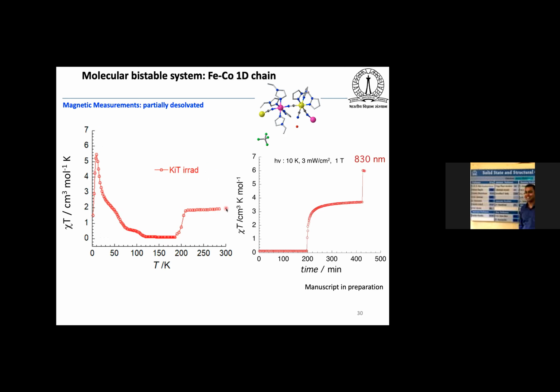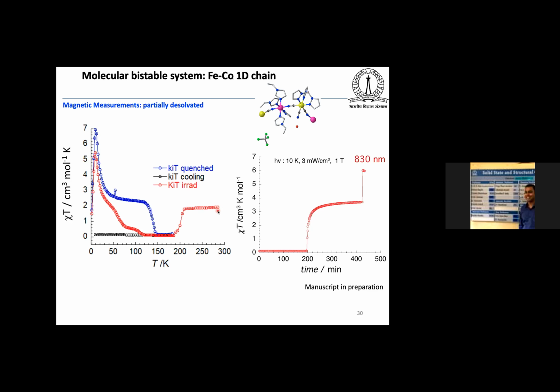And then when you increase it again to high temperature, because using this photomagnetic setup we cannot go to very high temperature, we have not measured it above room temperature. But we have performed this measurement using normal DC measurements. There we have observed that the system is showing two-step electron transfer. And here is the comparison plot, and you can see that the red curve is after light irradiation, and the blue curve is when we quench the system. You can see we can successfully quench almost the full state of the system, and the quenched state is completely different from the photo-induced metastable state.